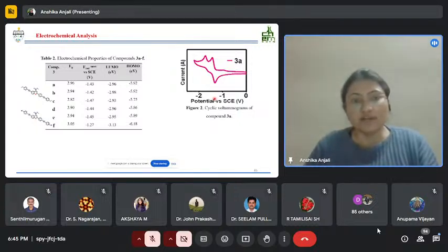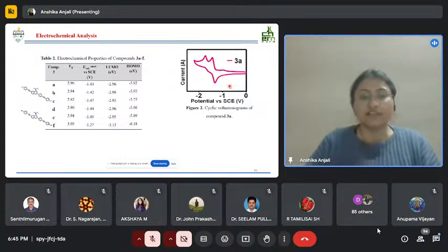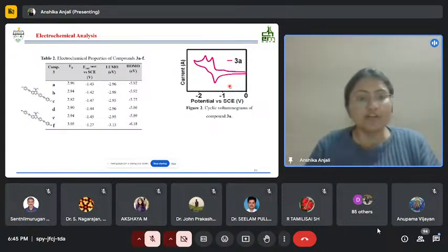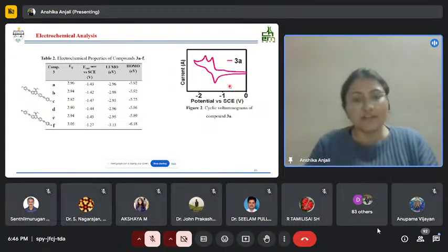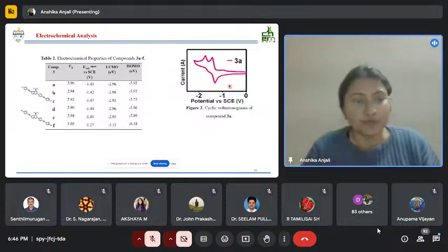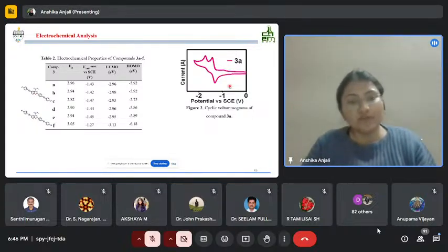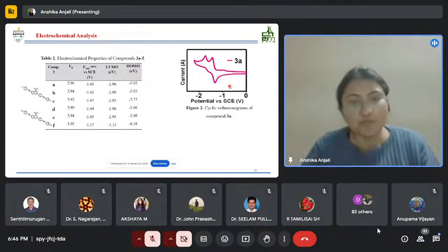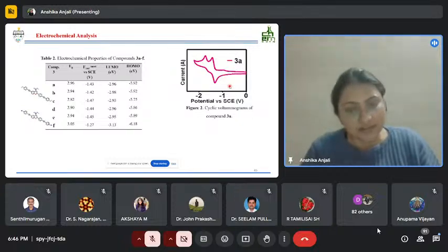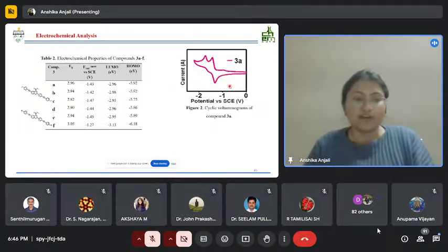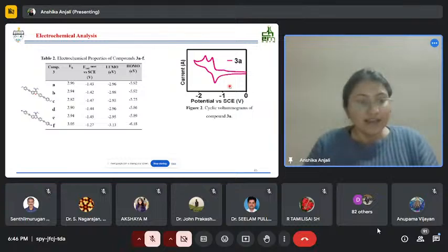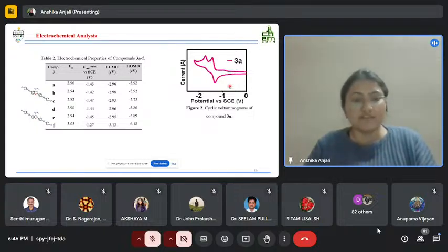So for these compounds, the cyclic voltammetric studies were done, and the cyclic voltammograms were recorded. And as we can see, these compounds resulted in peaks only in the negative potential. Thus, from their onset reduction values, their LUMO energy levels were calculated, and then from there we have calculated their HOMO and band gap values. Here for these compounds, their LUMO energy levels were in the range of -2.95 to -3.13, and their HOMO energy levels were in the range of -5.75 to -6.18 electron volt. And for compound 3C, we are having both high HOMO and LUMO energy levels. And for compound 3F with this cyano functionalization, we are having low HOMO and LUMO energy levels.